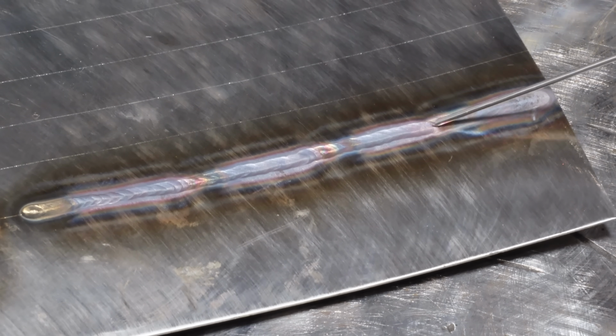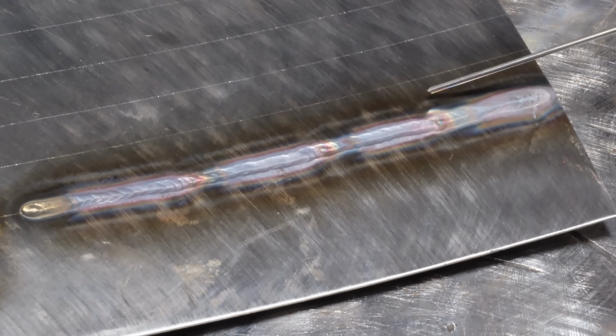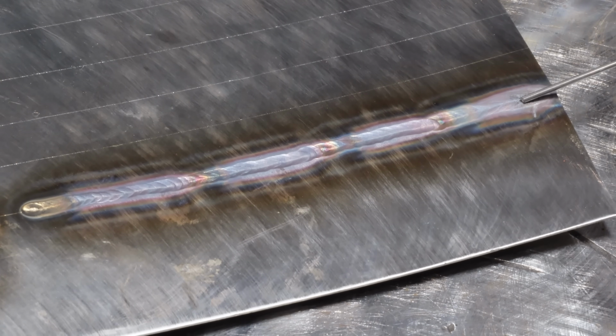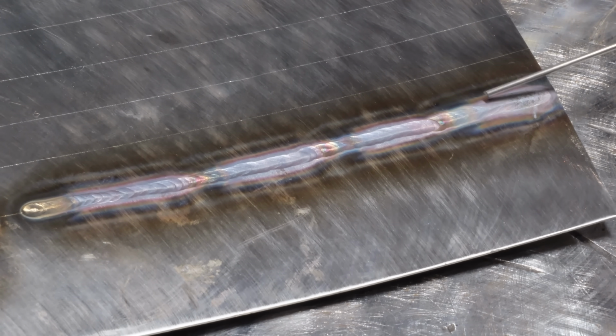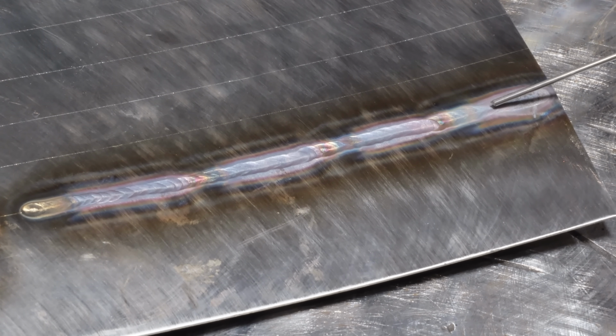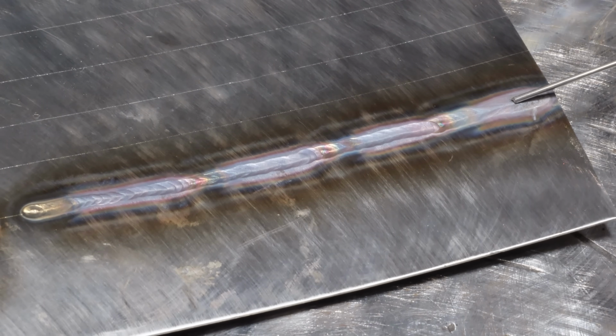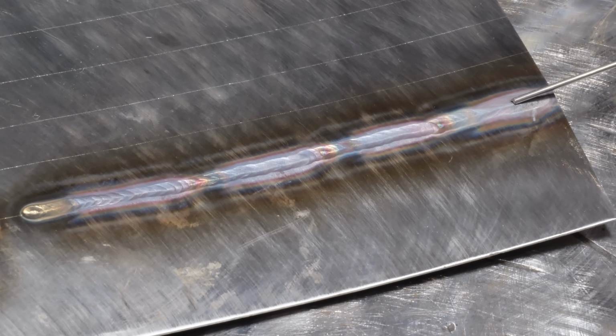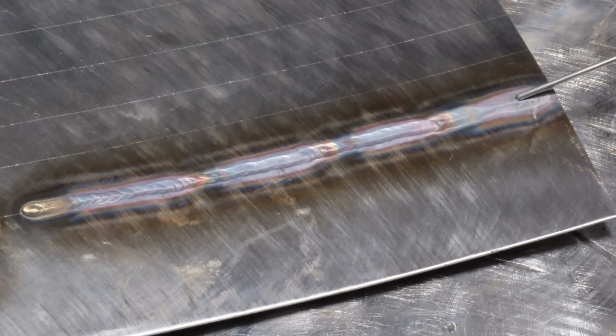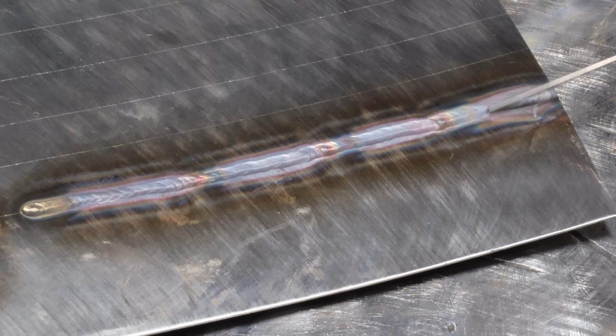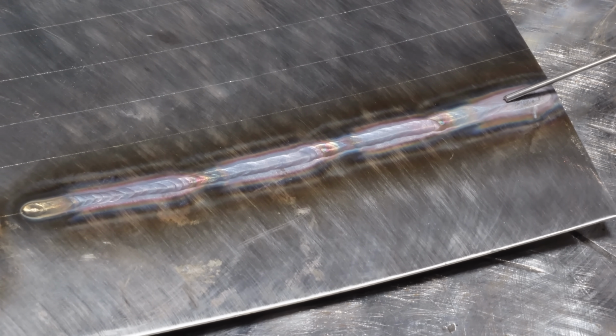One of the things that you really should notice here is how it has a V taper where there's a line down the middle. Anytime you see that, that's an indication that you have a lot of penetration, aka melt through, into the back of the material. Generally speaking, on thin material, that's not a desirable thing to see because you're typically only one pass welding this, and you more or less have a thin spot down the middle where it's likely to crack.